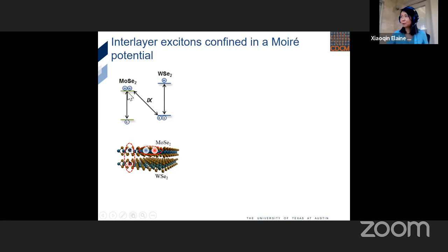So when I pick these layers with the same chalcogen atom, their lattice constants are almost identical. They differ by 0.1%. And now the Moiré size is really determined by the twist angle. There's a reason why we chose this combination: we want to see, can we make big Moiré cells, perhaps bigger Moiré supercells. First of all, it's a little easier to get to individually once we have the ability to use a near field measurement. And secondly, the size is completely determined by the twist angle.